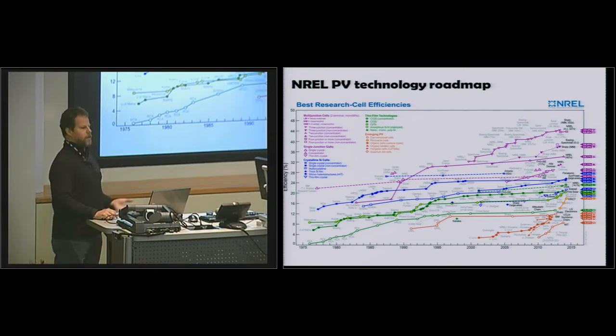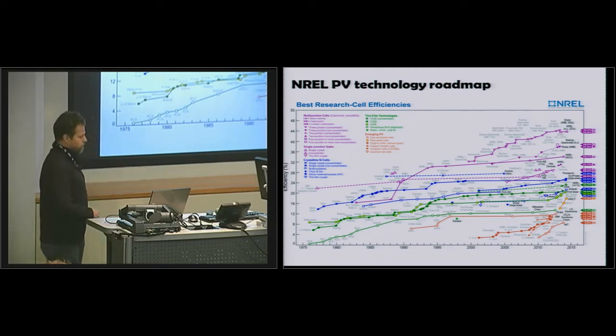Materials like gallium arsenide, cadmium telluride, and copper-indium gallium selenide are direct bandgap semiconductors and much, much stronger absorbers of light. So you only need a couple microns thick of material to absorb all the light. That class of materials is called thin film solar cells. Amorphous silicon turns out to have a direct gap, and it's also thrown into the class of thin film materials. So you have these III-Vs, these multi-junction cells, single III-V material.